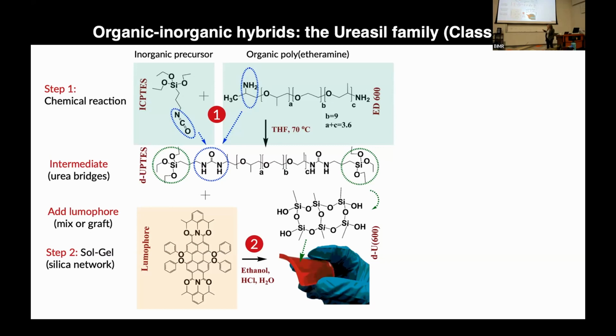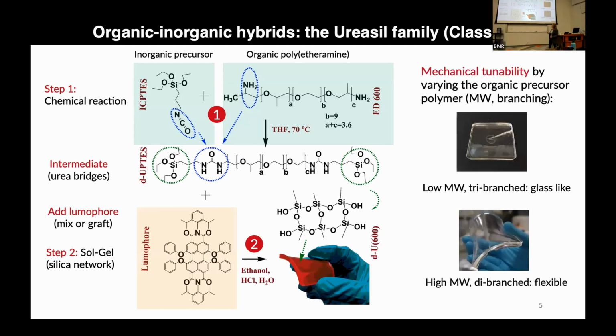To get the final material, then we just do some simple sol gel chemistry. We add an acid catalyst, bit of water, bit of ethanol, and this triggers the hydrolysis and condensation of this silica backbone. So we end up then with our final material, which is like a silica glass that's covalently bound via these polymer chains. And so by varying the nature of this organic backbone, we can tune the material's properties of the system. So for example, if we change the molecular weight or the degree of branching, then we can go from something that's quite glass-like, you can see this sample here, it's cracked, it's fractured because it's really brittle, to something, if we use a single chain polymer that's high molecular weight, that's really more flexible and bendy, like a pure organic material.